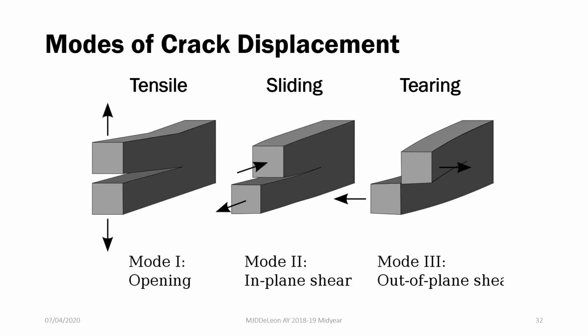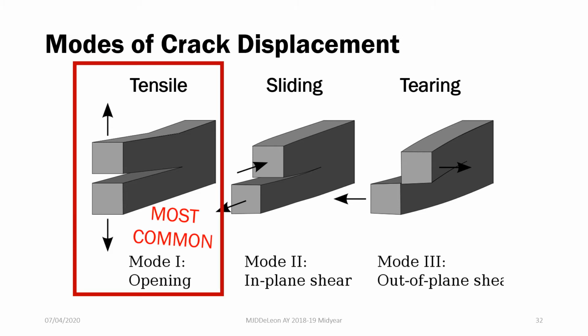In the propagation of your cracks, you also have three modes for the displacement or movement of your crack. First, we have your tensile mode, or the opening mode. You have your sliding, or your in-plane shear mode, and you have your tearing, or your out-of-plane shear mode. So between these three, which do you think would be the most common? Correct! So the most common is yung ating tensile mode. Since most of our stresses, makita natin pag nag-open yung crack mo, usually tensile yung behavior. Rin-rip apart natin yung bonds natin due to a tensile stress.